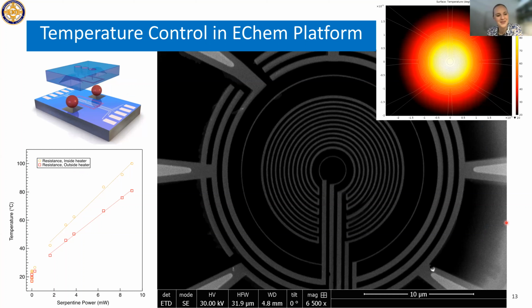I also wanted to bring up that with these electrodes, we can pattern heaters onto the platform. And so if you wanted to do temperature controlled experiments, they're very challenging, but they actually work really well. And this is just showing a resistance from this inside thermometer right here. Then you have a serpentine heater, and then this outer thermometer out here, and seeing the resistance to the temperature change shows that we can correlate that very well. And we also had a postdoc before, Dr. Andrew Lean here, who was able to confirm that with electron energy loss spectroscopy. So they're hard experiments, but they are possible.